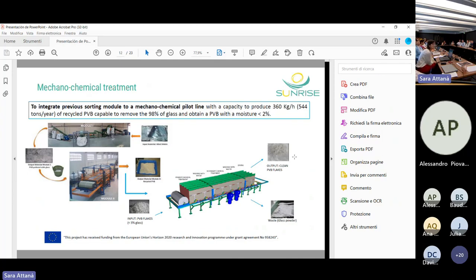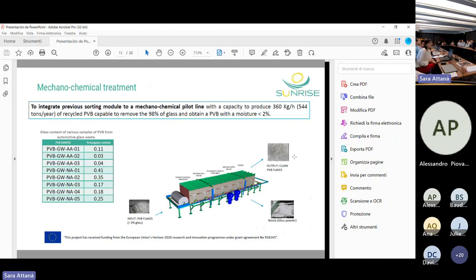This chemical treatment consists of 5 alternate washing steps, acid and basic cleaning, where the acid cleaning weakens the bonds between glass and PVB, and then the basic treatment neutralizes the previous step. So this is the process we make. Here are some results about the content of glass. Our target is having a glass content at the end of the process of 0.5%. These are some results of automotive waste where it's possible to reach this value and lower values.